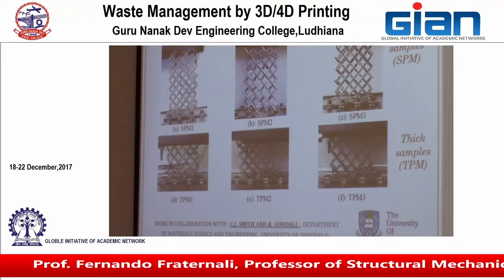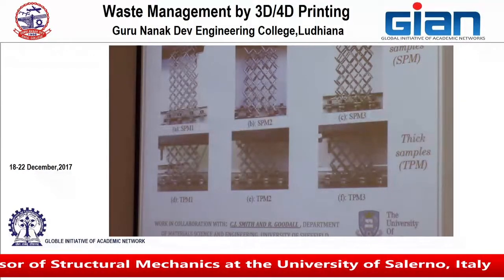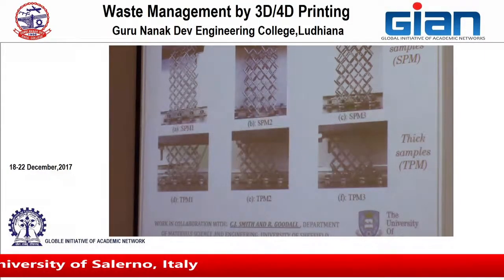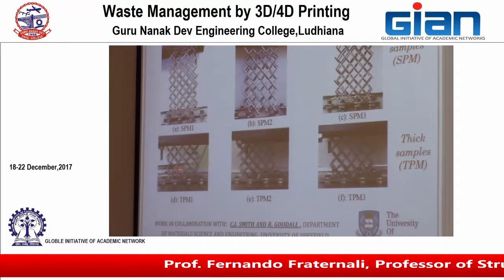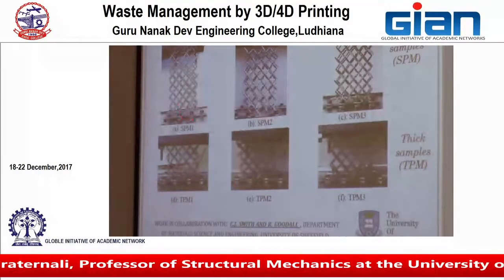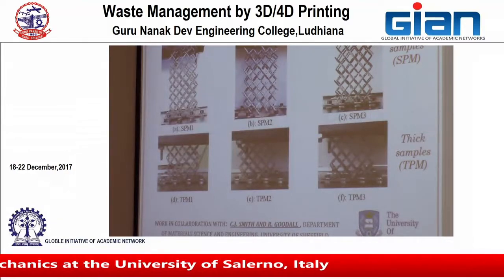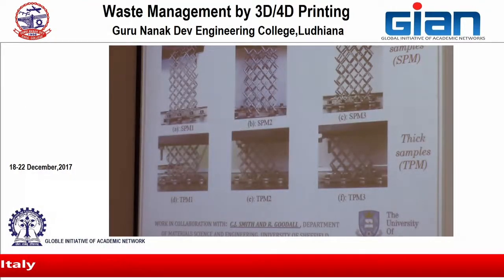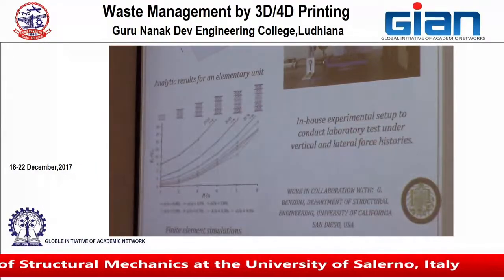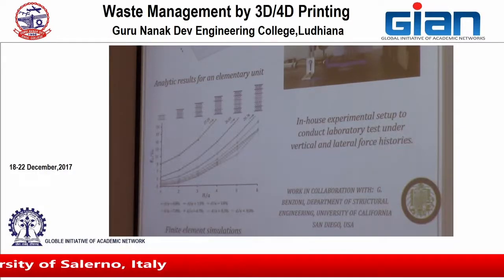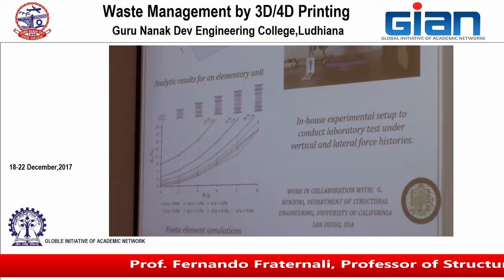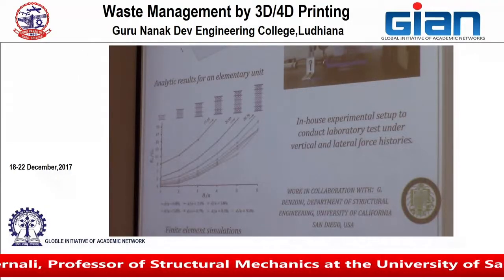And in doing this, we used some additive manufacturing techniques, and we built titanium alloy exemplars. Those were basically obtained by replicating, by changing the aspect ratio of the lattice, and inserted between stiffening plates. We studied the problem analytically, from the manufacturing point of view, and experimentally. And we obtained a series of results about the effectiveness of such structures